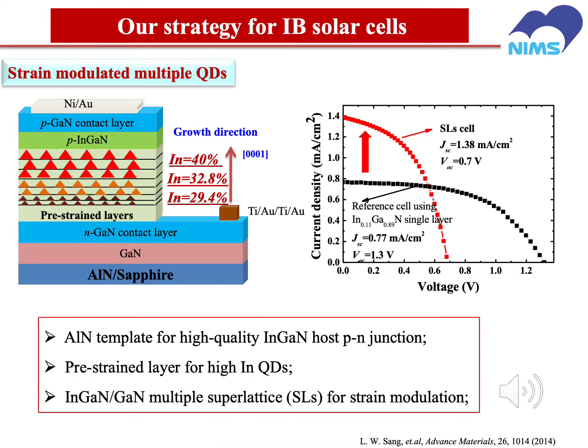So our strategy and our structure is like this. We introduced multiple indium gallium nitride quantum dots embedded in the quantum well structure as the absorption region, and this is inserted between the gallium nitride p-n junction to achieve the intermediate band transition. So the multiple intermediate bands are achieved by changing the indium composition in the quantum dots, and this is achieved by a strain modulation method. And here is the IV characteristic under the solar simulator illumination. We can see that by using this structure, the short circuit current density can be greatly enhanced.